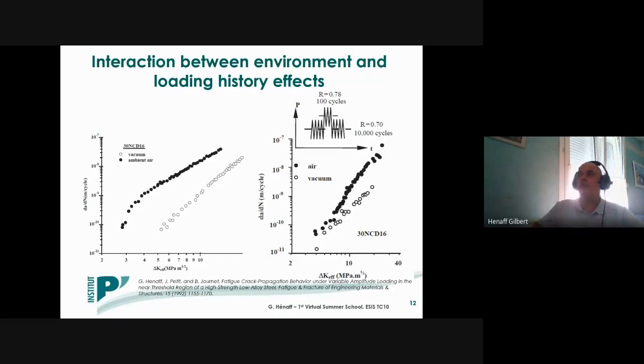So the idea is to introduce some overload effects, which is supposed to induce a retardation in fatigue crack propagation. And indeed, when we compare, for instance, in air, the fatigue crack growth rates obtained with this type of loading compared with constant amplitude loading, the rates are delayed by this type of overload. However, when we compare the rates obtained in air and in vacuum under this type of loading, we can see that we have almost no environmental effects in the low delta K region, and that environmental assistance only appears when we increase the delta K value.